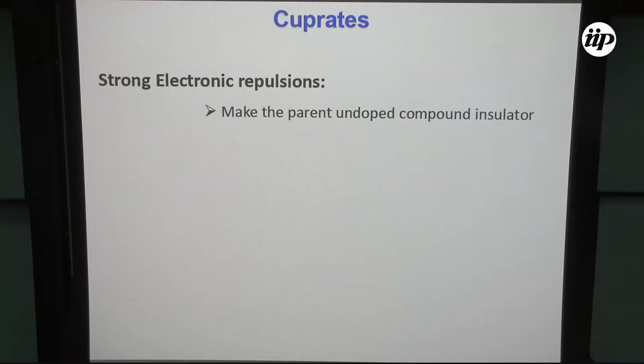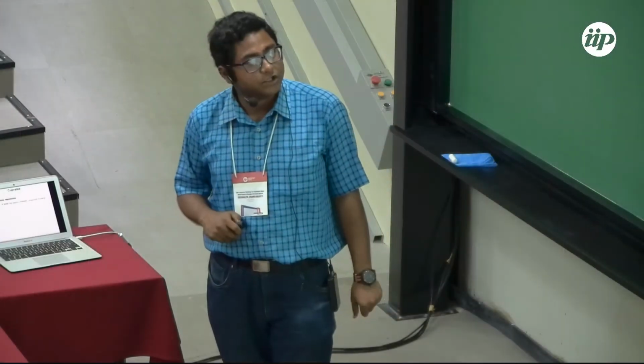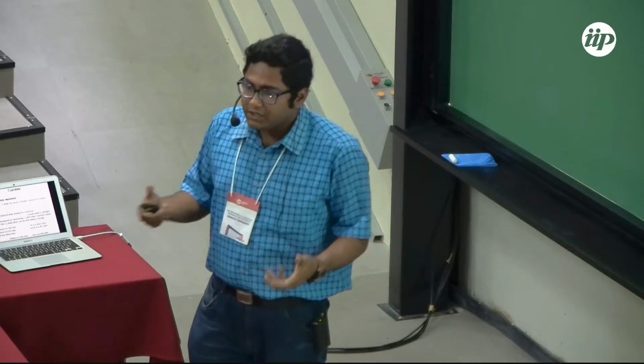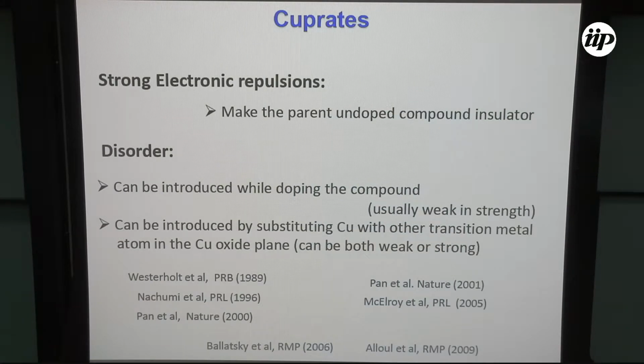We know that cuprates are strongly correlated materials, because at least at half filling, it's a Mott insulator. So strong correlation is important in these materials, at least at half filling for sure. Also, we know that disorder is ubiquitous in cuprates. For example, if you dope the sample, you introduce out-of-plane disorders, which are considered mostly to be weak. You can also substitute the copper ion by some other transition metal ion in the copper oxide plane. Those are called substituents, which also introduce impurities. They can be weak or strong depending on which transition metal ion you are using.